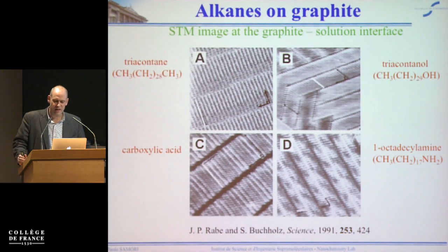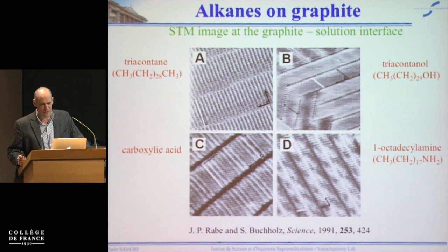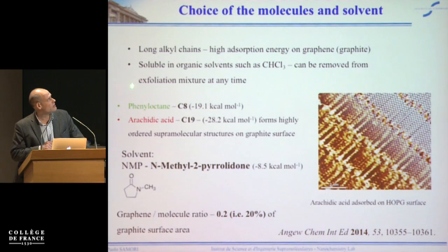These lamella structures are highly ordered, and this is evidence that there is a very strong affinity through van der Waals interaction between alkanes and graphene or graphite. And so this is what I thought. We use a long alkyl chain that has high adsorption energy for the basal plane of graphite. It is soluble in organic solvent.